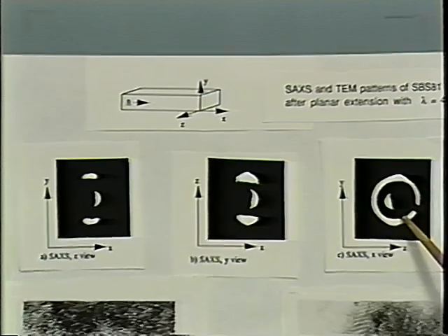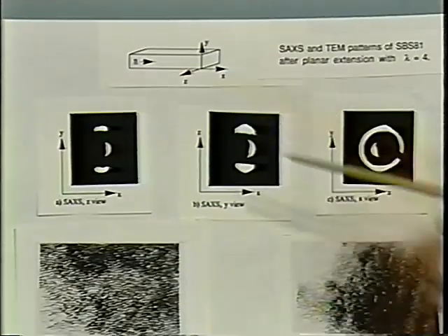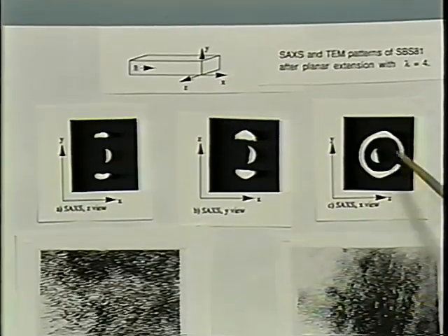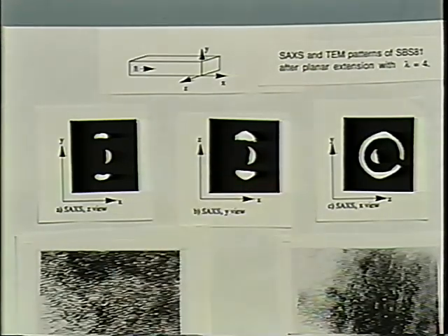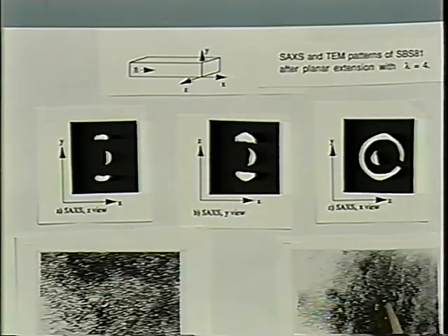That means that the cylinders are aligned in flow direction, in X direction, but the hexagons are still rotated randomly, and you can see this when looking at the micrograph. There's a rotation here in the hexagon.